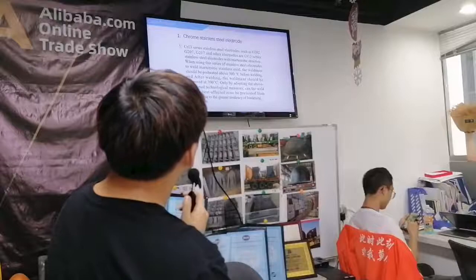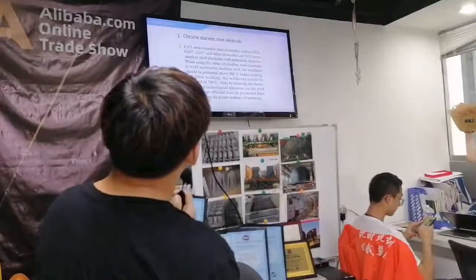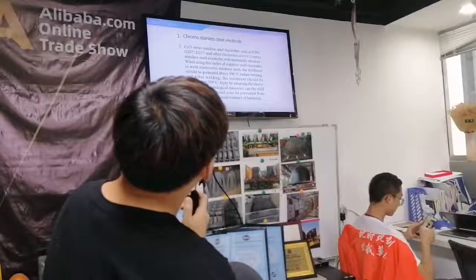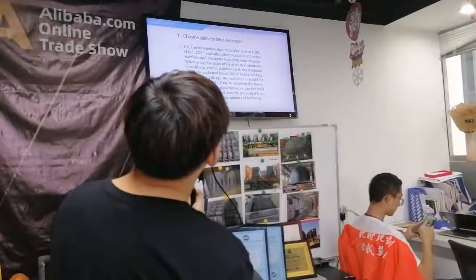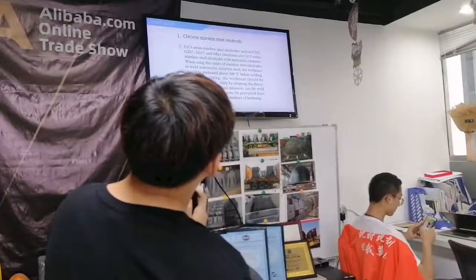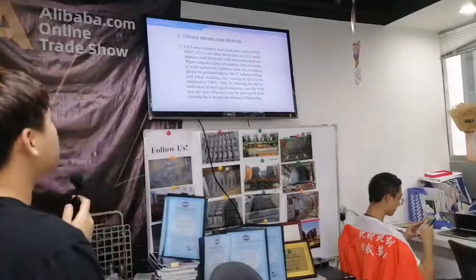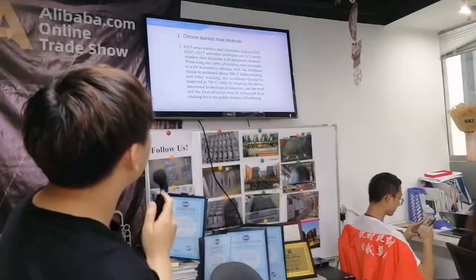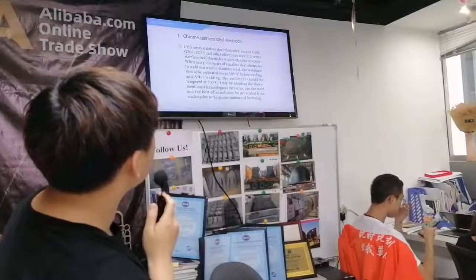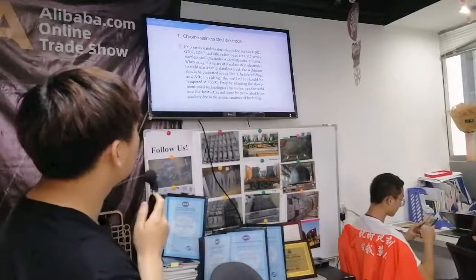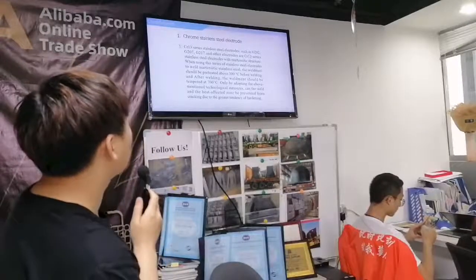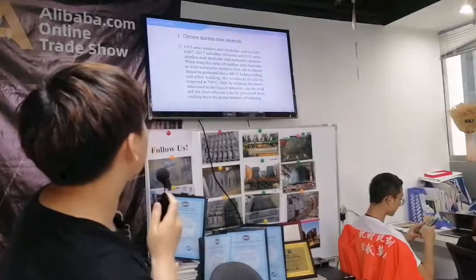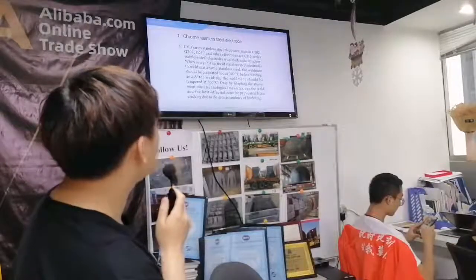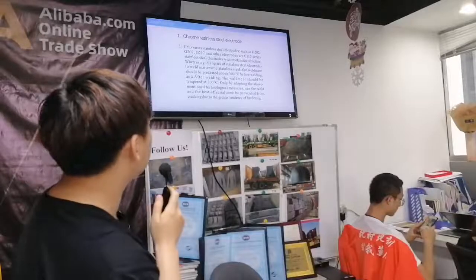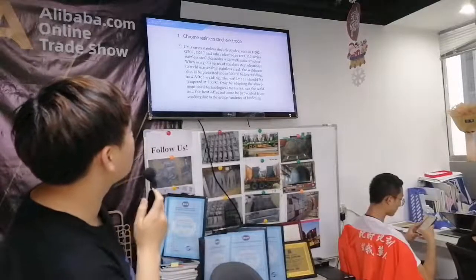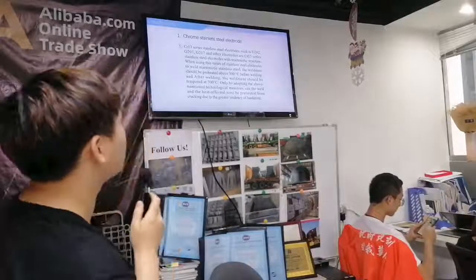CR13 series stainless steel electrodes such as G202, G207, G217, and other electrodes are CR13 series stainless steel electrodes with martensitic structure. When using this series of stainless steel electrodes to weld martensitic stainless steel, the weldment should be preheated above 300 degrees before welding, and after welding, the weldment should be tempered at 700 degrees. Only by adopting the above-mentioned technological measures can the weld and the heat-affected zone be prevented from cracking due to the greater tendency of hardening.